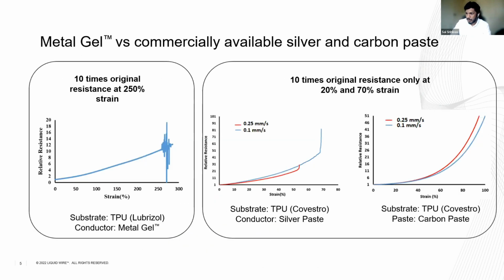Speaking of the performance of the metal gel, on the first graph you see we have laminated a single layer of metal gel in between two pieces of TPU, and we stretched it up to 250% strain, but the relative resistance just went up 10x from the initial value. Whereas other commercially available silver inks or carbon paste reach 10x of the initial value at just 20 to 70% strain. So it shows how reliable metal gel is over a huge range of stress conditions.